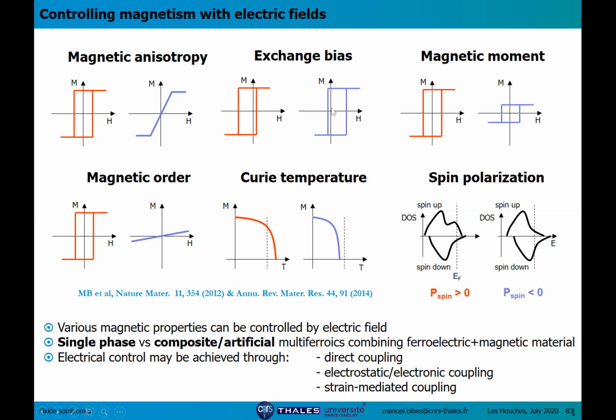You have exchange bias. Exchange bias is a shift of the hysteresis loop induced by an antiferromagnet. If you control the spin structure in the antiferromagnet, maybe you can switch the direction of the exchange bias. You can also maybe control the amplitude of the magnetic moments. You can also control magnetic order, going from ferromagnetic to paramagnetic, or from ferromagnetic to antiferromagnetic. You can maybe control the Curie temperature, so that when you operate at a given temperature here, your material will be either ferromagnetic or paramagnetic. And as I've shown in the previous slides, you can also control spin polarization.